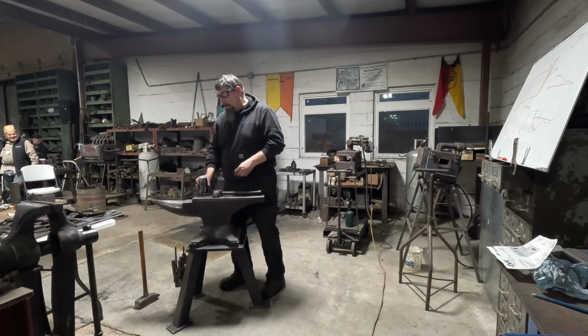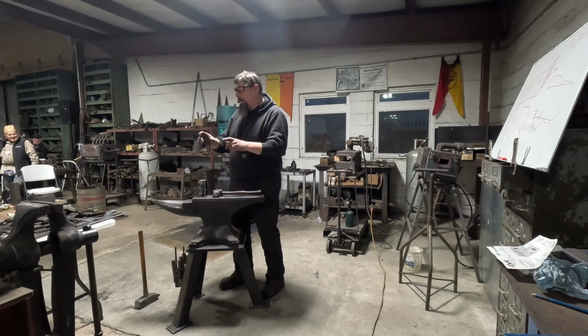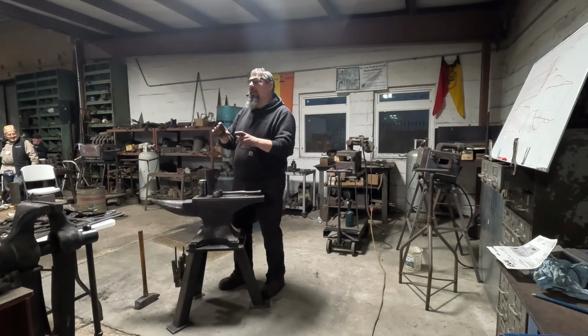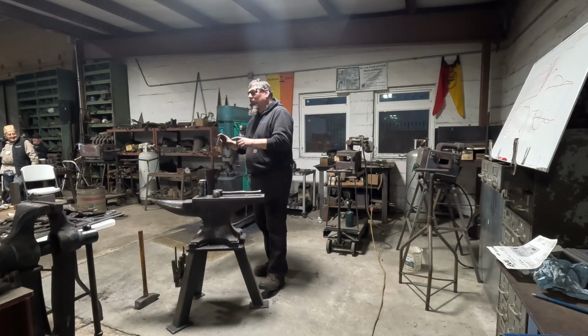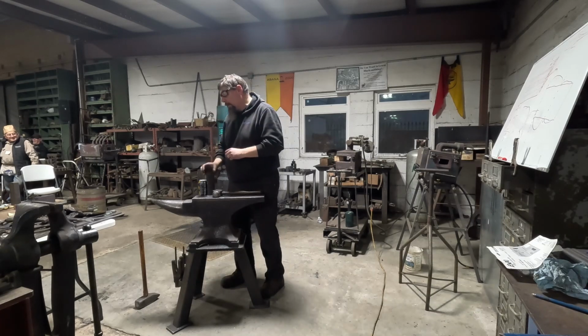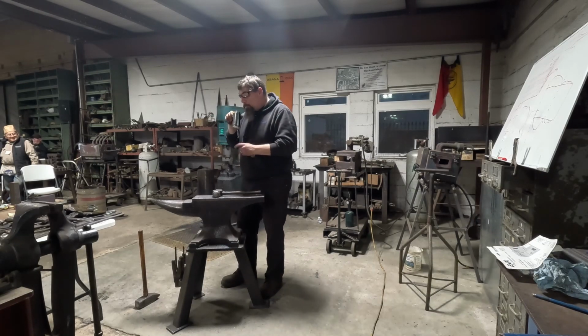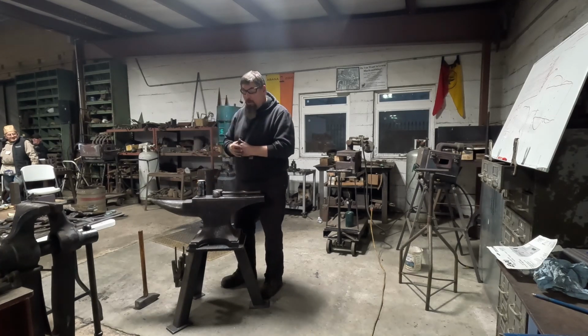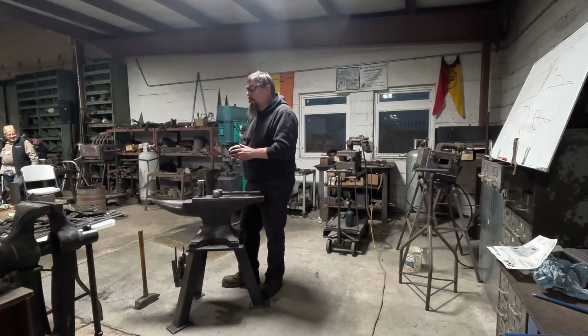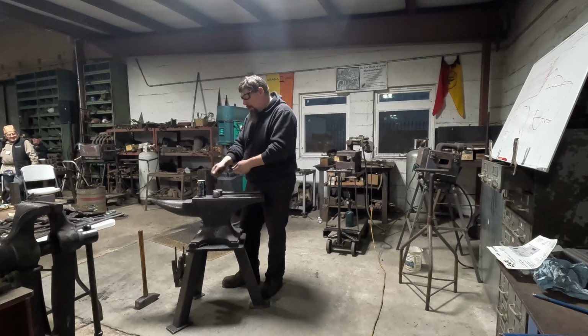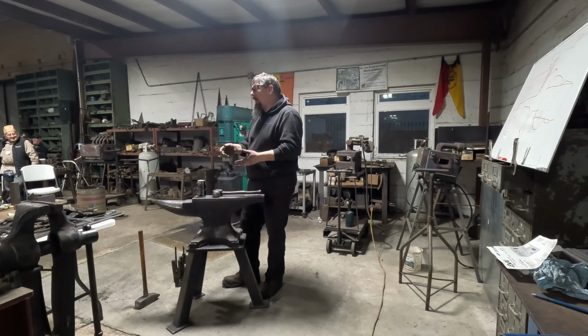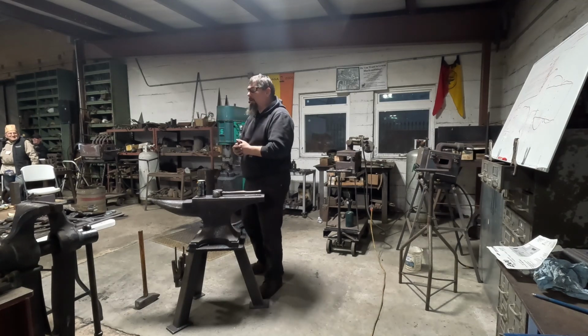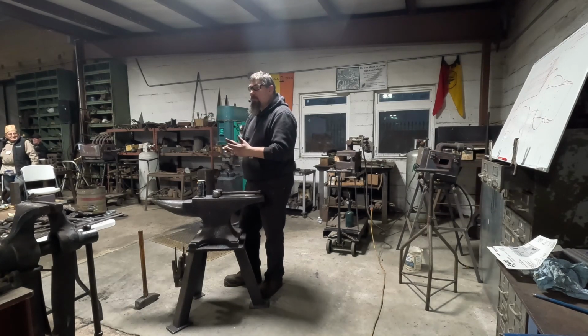So what I did was, and if you're paying close attention, you'll recognize that I'm bringing in testing: how do we do testing in the blacksmith shop when we don't have a fancy lab like I have at work? So what did I do? I cut a little piece off and put it in the forge and intentionally heated it to a relatively low temperature. And then I took a cable and pounded on it a little bit. Because if it were wrought iron, especially like the puddled wrought iron that we were discussing earlier in the day, forging it at low temperature would probably cause it to crack apart and crumble, and people have all kinds of challenges with that material. So I thought, well, we'll try to rule that out right away.